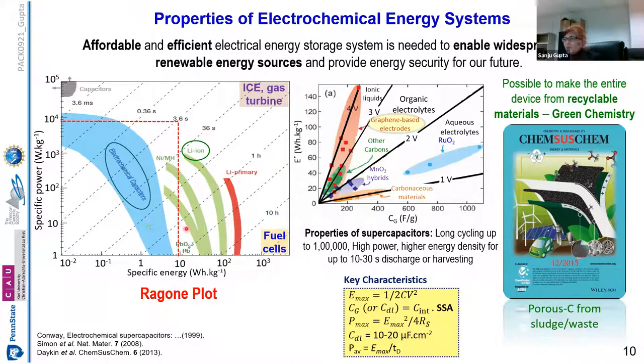So it's an interplay, and that's where the drive towards the development of engineered electrochemical electrodes comes into the picture. And then of course, other than aqueous electrolytes, if we look at the key parameters, the energy is basically half CV squared. So I can increase this energy either by increasing the capacitance, which I just described, or by increasing the operating potential window. In order to increase the potential window range, other electrolytes came into the picture, like organic electrolytes or ionic liquids.